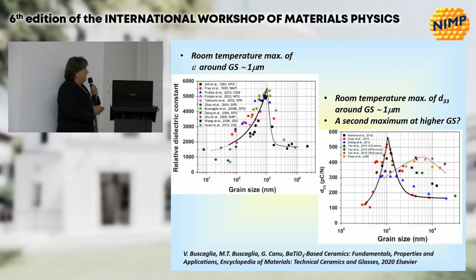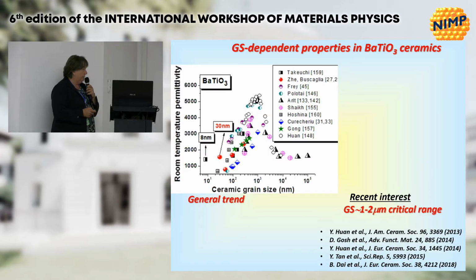Well, some recent data, this diagram has been updated as of last year. And in addition, as I forgot to say, not only permittivity, but also piezoelectric coefficients show a peak around 1 micrometer. But more recent data and a better collection of data has been done by the group of Vincenzo Buscaglia. According to them, as I discussed before, there is a second maximum here. I would say that is a very spread data collection in this range, but anyway, there is a clear maximum around 1 micrometer. Traditionally, the mechanism for this maximum was considered similar both for permittivity and for d33, but there is a discussion about this. Maybe I'll have time to say.